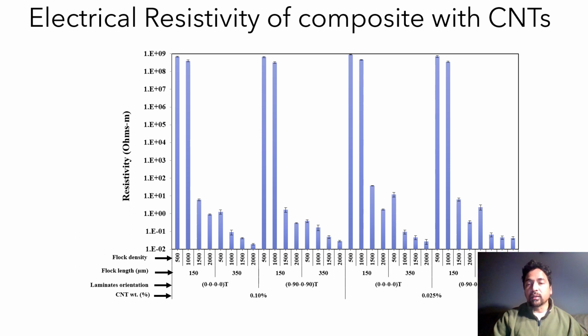We deliberately put these small amounts because carbon nanotubes are very expensive and we do not want to put too many, and we want to achieve the required electrical resistivity with a smaller amount of carbon nanotubes. As you can see in this picture, the amount of carbon nanotubes did not play a significant role. You see a similar trend for 0.1% and 0.025%. Very marginal difference you can see between that. However, if we look at the laminate orientation, there is some decrease in the 0/90 orientation compared to the 0/0 orientation for both carbon fiber lengths.